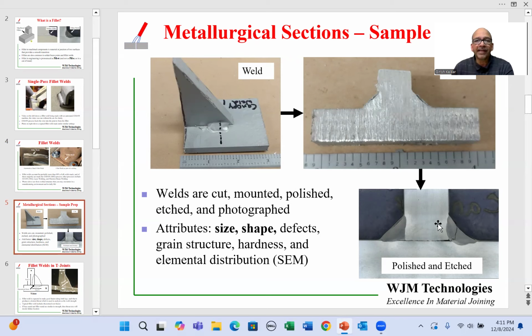And then the lab will take a photograph and email it back to you, and this is what you're going to see. In this case over here, we can see that there are two components which have been welded. There are two fillet welds, one on either side, and we can see the volume of metal which actually melted during the welding process has a different contrast than the volume of metal which did not melt. So the ones which did not melt are lighter gray in appearance over here, and the darker gray ones are those which melted. Again, these contrasts can be different depending on the metallurgy. In this video, we are going to focus more on the size and shape of the fillet welds. We can glean a lot of information about the defects, grain structure, hardness, and elemental distribution of fillet welds from these cross sections, but we're going to save that for a later video.